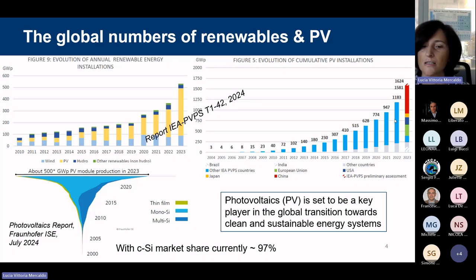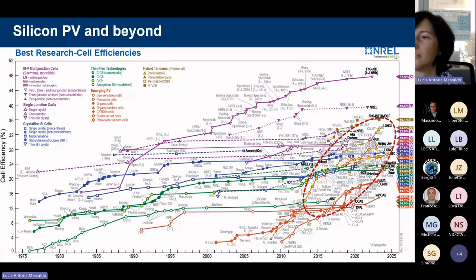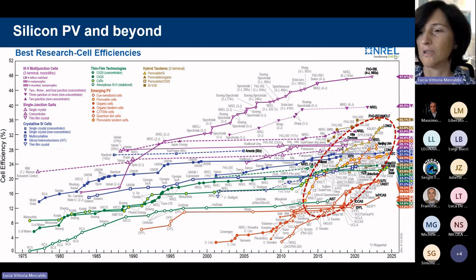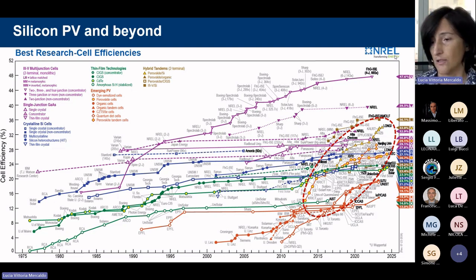As for the technologies, the market is dominated by crystalline silicon. The crystalline silicon market share is currently around 97%. This is also because silicon has been around for quite a while. In another chart here we can see that other contenders came into play recently, and so perovskite solar cells have now emerged as a very promising technology, not only as an alternative to silicon, but also together with silicon in tandem designs, where perovskite and silicon are applied together and can go beyond the efficiency limit of single junction solar cells.